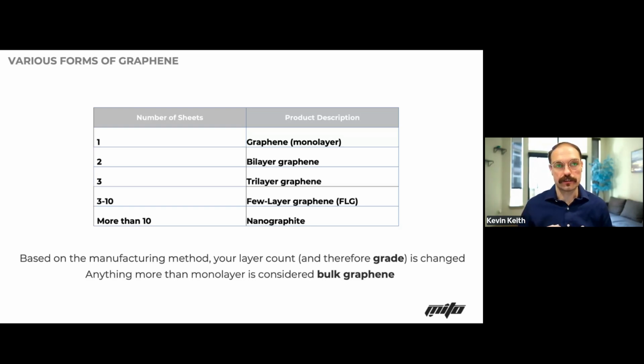Very chunky, dense material. It's not a bad material, but you have to realize what that chunky, dense material can really be plugged into, and start adjusting your expectations that, hey, if I try to disperse this into a resin that has 9,000 centipoise, it's not going to go well, and it's going to crash out eventually. So just have to adjust that expectation of how you're going to apply that really chunky material.